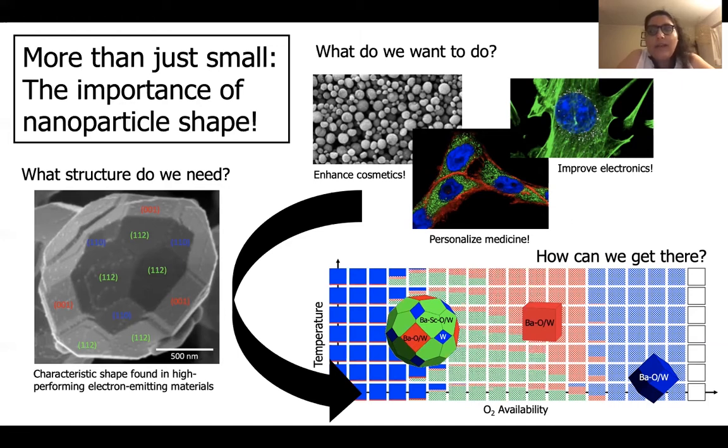So I took a step back and approached the problem from first principles. I worked to identify the specific combination of temperature and chemical environment that could produce this characteristic shape. But there's a major obstacle. Results from first principle quantum mechanical calculations are always at 0 Kelvin, which is absolute zero. This isn't really a great approximation when cathodes are being operated at over 1,000 degrees Kelvin. My work is focused on incorporating finite temperature into these calculations so that we can get a bigger, clearer picture.